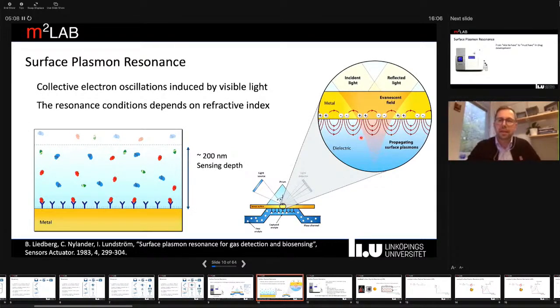These propagating surface plasmons are essentially collective electron oscillations that are induced by visible light, and which result in an evanescent field that propagates into the surrounding medium. That's what is being illustrated here. And that evanescent wave reaches out roughly 200 nanometers from the surface into the surrounding, which makes this a fairly surface-sensitive technique, so we can monitor what goes on close to the surface here.